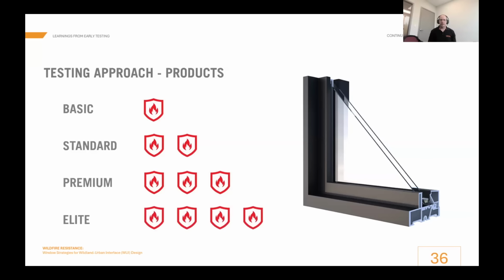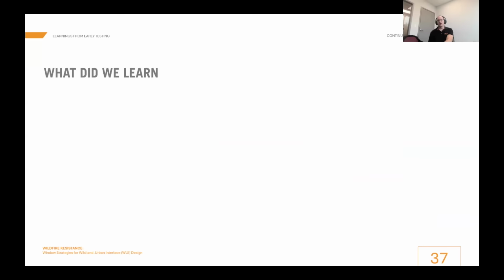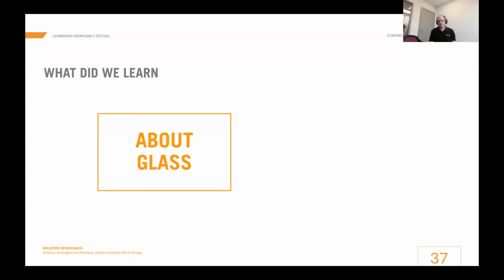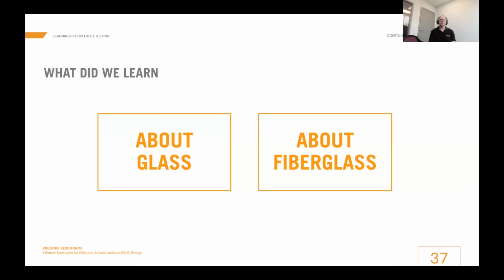And then the final one was, let's go to a laboratory that builds glass for chemistry work and get some fireproof glass, and let's pop that in there so that we can isolate the damage and observations to just the frame. Then we tested these, and they all worked, even the most basic one, which really surprised us. But more specifically, we learned separate things about glass, and we learned about the frames, and in this case, fiberglass specifically.